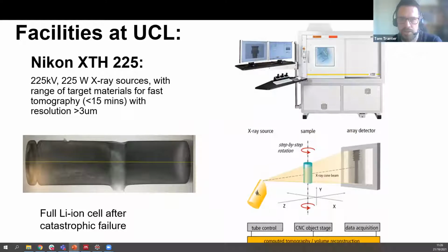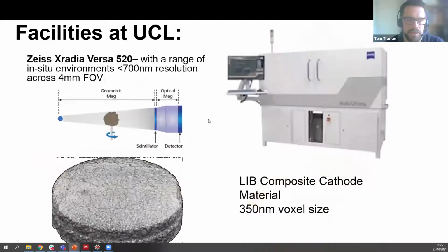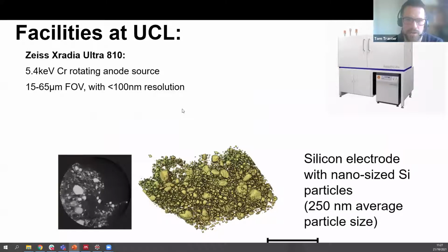So we have 3 machines in our lab, in the Electrochemical Innovation Lab at UCL. The one with the largest field of view is the Nikon, and we can now scan a whole battery in about a minute, and we find that the quality of the image at that level is acceptable for some of the analysis that we undertake. We have a slightly better resolution machine in the Xradia Versa, and we can zoom in to single layer images for that one. And then for the particle level, we have the Xradia Ultra, and that can get very high resolution of hundreds of nanometers.